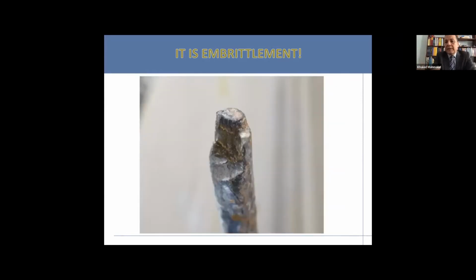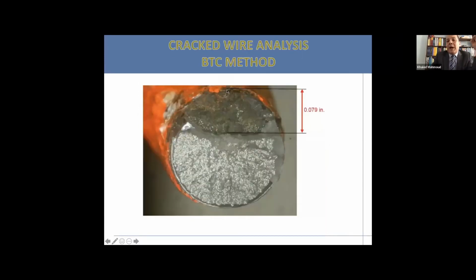This is yet another example of a brittle break, where you see the crack starting here, and again, this is what we call stepped fracture. So what happens is you have the edge crack starting here and the further crack propagation. Why is this important? This is extremely important because it gives us insights on how to maintain suspension cables and how to maintain their service for much longer time at a reduced cost. It is a very expensive proposal to replace a bridge cable.